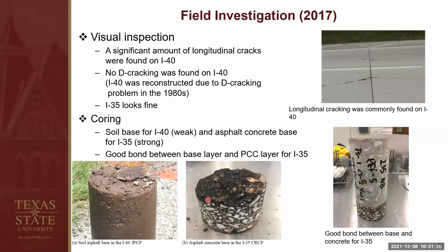We saw a lot of longitudinal cracks on the I-40, but we did not see any D-cracking on I-40. Remember, I-40 was reconstructed due to the D-cracking issues in the 1980s. For the I-35, everything looked fine, and we also extracted some specimens from the fields, and we found that on I-40 the base material was weak. It is asphalt treated soil base, as you can see. It's pretty weak. But for the I-35, the base was asphalt concrete. As you can see, the bonding between the asphalt and the RCA concrete was still good, as you can see from the sample here.